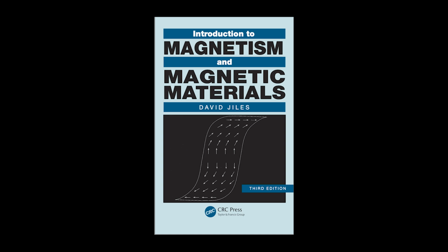And structurally, soft ferrites are actually ferrimagnets, not ferromagnets. What's the fundamental difference there? In a ferromagnet, like iron, all the neighboring spins are aligned parallel. In an antiferromagnet, they're anti-parallel and equal, so the net moment is zero. Okay. In a ferrimagnet, the neighboring spins are also aligned anti-parallel, but they are of unequal magnitude. This leads to a substantial net magnetic moment, similar to a ferromagnet, but the non-metallic ceramic structure gives you the high resistance you need for high-frequency work. So you're using anti-parallel alignment to solve an engineering problem, the eddy currents.